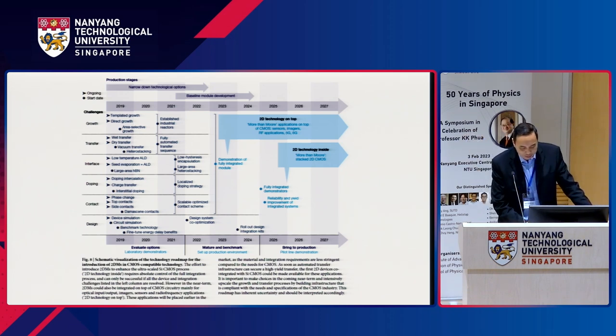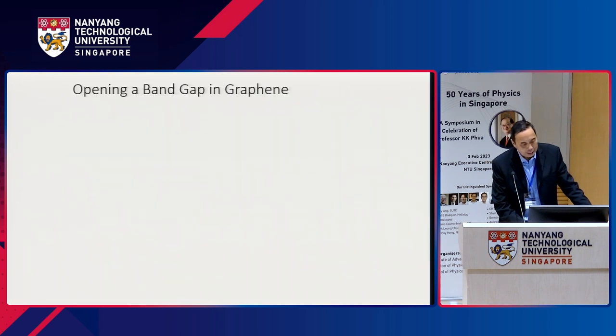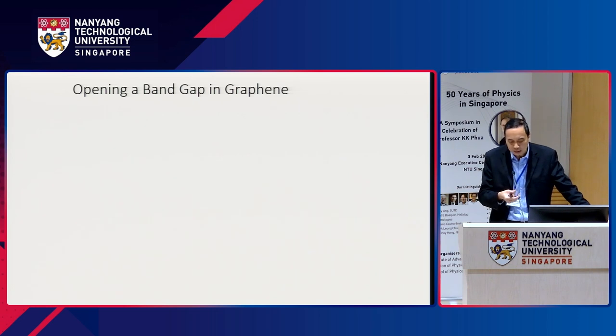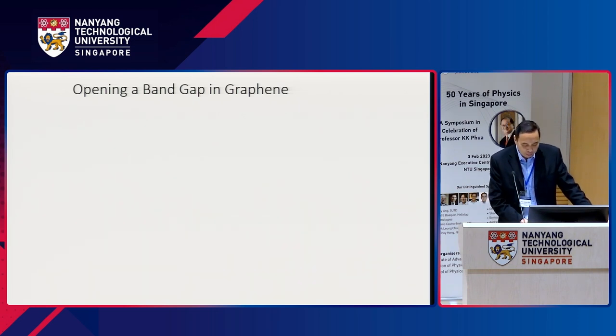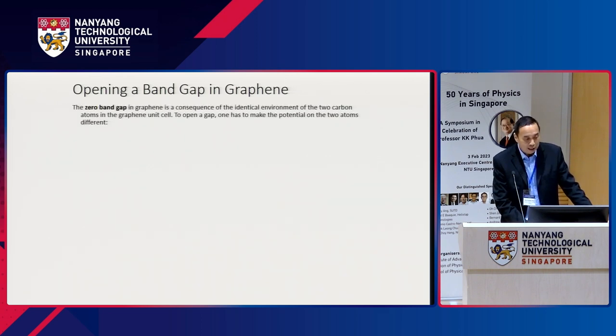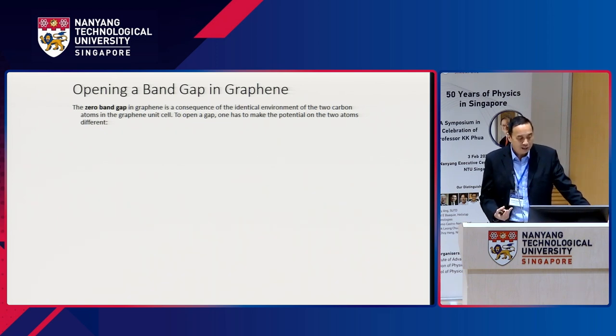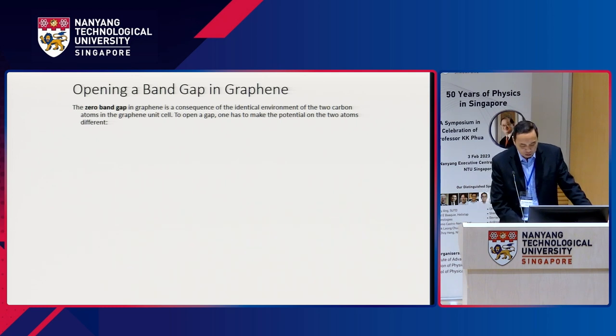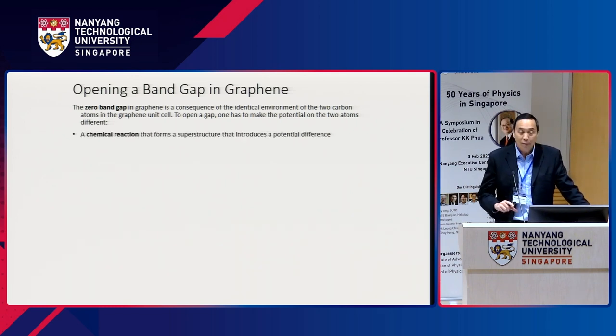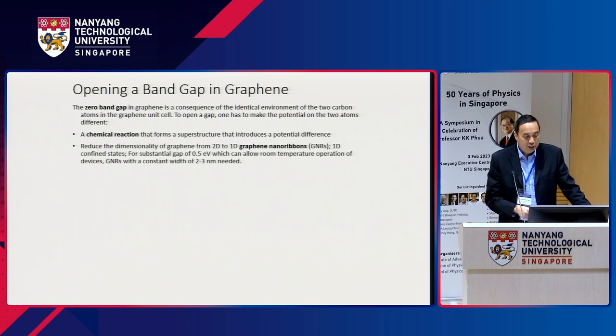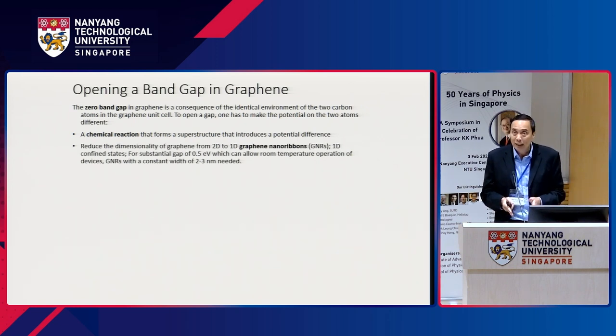But the problem with using graphene, as it was found out, is that graphene is a semi-metal, so it's not the ideal thing to work on because it's a semi-metal and not a semiconductor. So we needed to open a band gap in graphene, and popular ways of doing so exploit the fact that there are two identical environments of two carbon atoms in a graphene unit cell. So you have to make the potential different. One way is a chemical reaction, so you form a superstructure that introduces a potential difference. Another way is to reduce the dimensionality of graphene from 2D to 1D, so you make graphene nanoribbons, but you have to make them fairly small in order to get substantial band gaps, so that's fairly difficult.